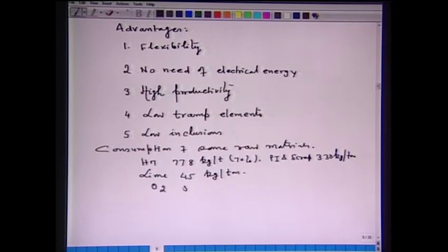Oxygen, which is important, 50 to 70 cubic meter per ton. Then fuel that is also use 5 to 10 megacalorie per ton. Tapping temperature is 1700 degrees Celsius without ladle furnace, and it is 1650 degrees Celsius with ladle furnace. So, this is about the energy optimizing furnace.